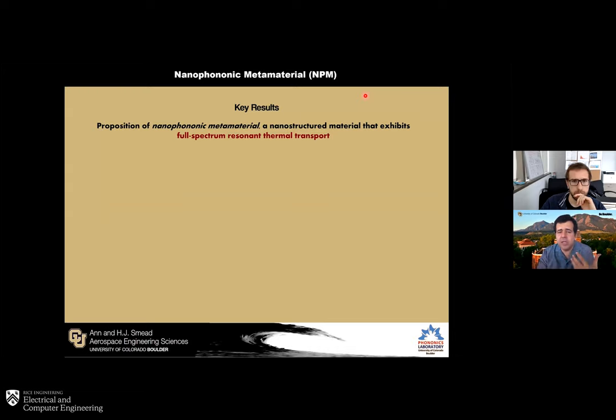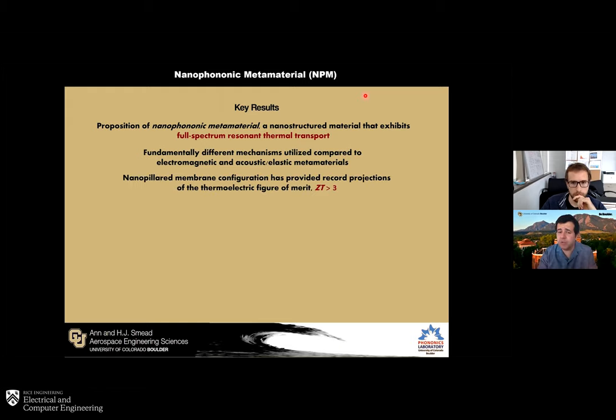So we have this notion of an NPM, and what is unique about it is that it utilizes resonances in the full spectrum. As I said, practically millions of resonances, and it allows us to, in a way, really transform the very character of thermal conduction at the nanoscale. It becomes essentially a resonant dominated thermal transport, and we've shown that this is very different from the conventional mechanisms of electromagnetic and acoustic metamaterials. And with some projections, we are targeting high performance in the area of thermoelectrics with this configuration.